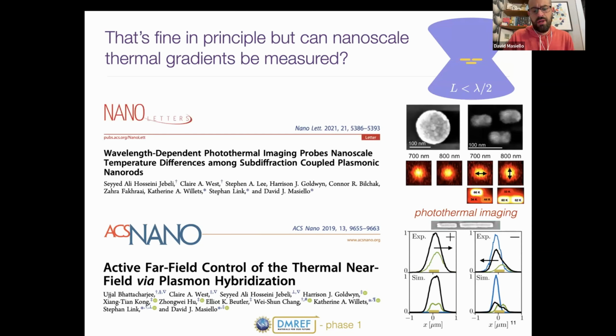We then went on and shrunk the nanosystem down to a trimer system. I don't recall if it was gold or silver, it doesn't matter, but the particles are three of them, and they are all three smaller than the diffraction limit of light. Again, they performed photothermal heterodyne imaging and saw no gross leftward or rightward biasing of the photothermal image function. Instead, what we were able to do was tease out, based on changes in ellipticity of the photothermal image function compared to that of a reference disk on the same slide as these trimer structures, we were able to correlate, again with theory, changes in ellipticity back to thermal gradients that were getting set up, either running in the Y direction or the X direction, if you will, on this trimer system.